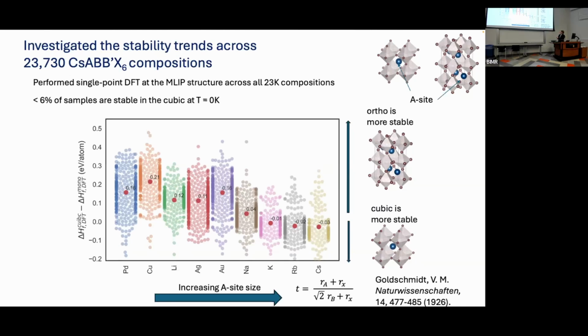And what this tells us is that effectively the ratio of the A site radius and the B site radius, scaled a little bit, really determines whether or not something will form the structure. And conceptually that makes sense because the A site sits and holds these octahedra together. And so if the A site's too small, the octahedra will collapse on themselves. It'll go from corner sharing to face sharing.